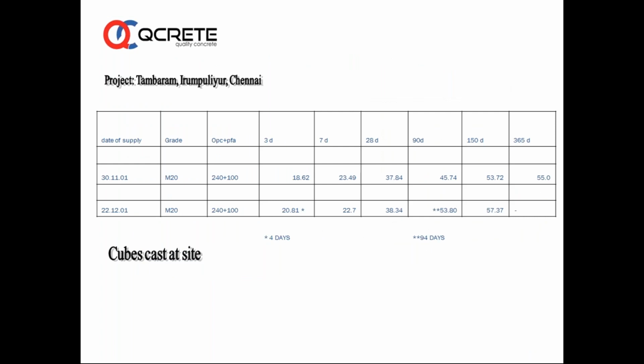A customer purchases a concrete with 240 OPC and 100 fly ash. This fly ash was from the Ennur thermal power plant near Chennai. When we use this 240 plus 100, with a water cement ratio around 0.49, the 28-day strength is about 37 or 38, and there is a rise of the strength to about 55 newtons in 365 days.